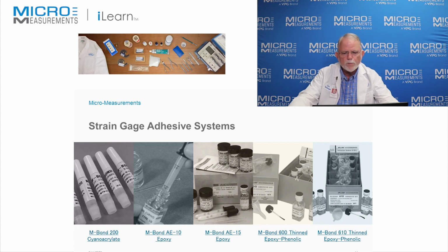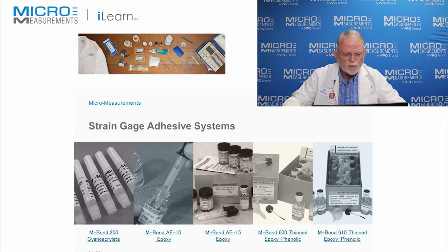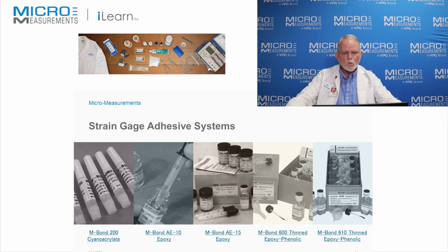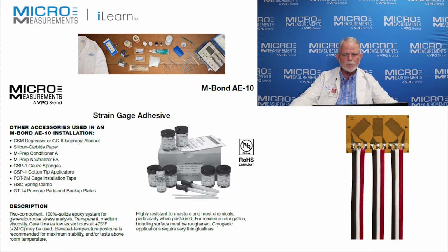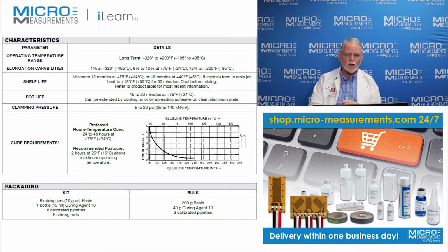All right, let's talk about some of the parameters that you would use to select the adhesive system. The first thing, and probably the one that's going to be most critical, is its operating temperature range. I'm looking at here the data sheet for M-Bond AE10, and its operating temperature range is -320, call that liquid nitrogen, all the way up to 200 degrees Fahrenheit, boiling water. You can extend that above 200 degrees Fahrenheit, but at that point it begins to get a little creepy. The bond line will get a little soft, and so you might have a problem with static measurements. But dynamic measurements all the way up to a couple of hundred degrees Fahrenheit is quite easily done.